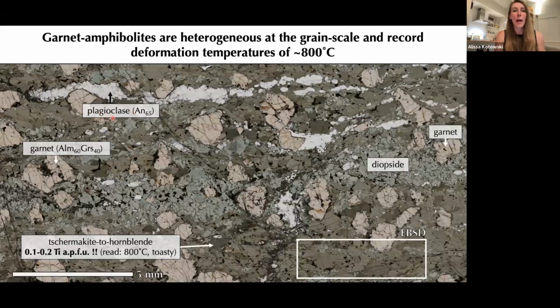Looking at the mineralogy, we have plagioclase here with high anorthite components. We have happy almandine-rich garnets here. And the composition of the amphibole is tschermakite to hornblende. The amount of titanium that can go into an amphibole is very sensitive to temperature. So if you measure the amount of titanium in the amphibole, you can actually use that to calculate a metamorphic temperature. So these minerals have about 0.1 to 0.2 titanium atoms per formula unit, which is relatively high. So this is telling us that these garnet amphibolites are forming and metamorphosing and deforming at about 800 degrees Celsius.